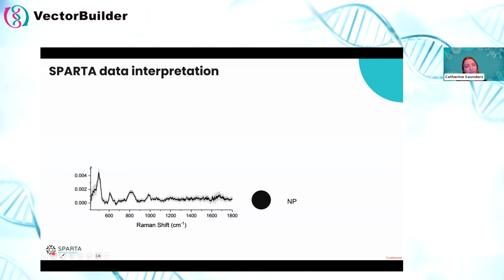We can visually see there are some clear peaks, and these correspond to specific bonds present in this nanoparticle. And the nice thing about Raman spectroscopy being an experimental science for 100 years is that all these peaks are very well documented. So as a sanity check, we can also compare these peaks to databases, and they will not substantially shift in position. So we can, for example, take these peaks and assign them to the base nanoparticle.